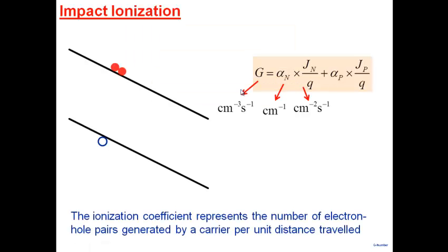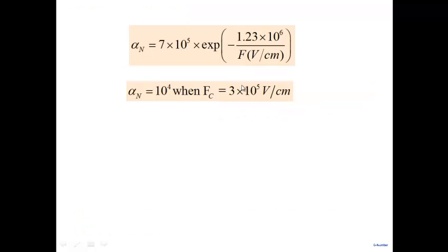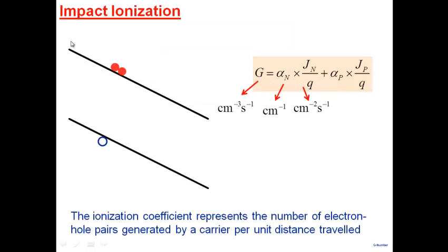And remember, impact ionization, what will it do? Suppose you have a piece of semiconductor and you have very little current flowing through it. Imagine a PN junction in reverse bias. Very little current flowing through it, but there's a small amount of carriers that are flowing, right? Now imagine that I have applied a voltage large enough so that the field is close to this value or a little larger. Then what will happen is an electron, a very little electron which enters here, moves in, creates another electron hole pair. These two electrons then move in further, then they create more electron hole pairs, and therefore we have what we call avalanche multiplication. And therefore I can have very high currents, and this is what you know as breakdown.